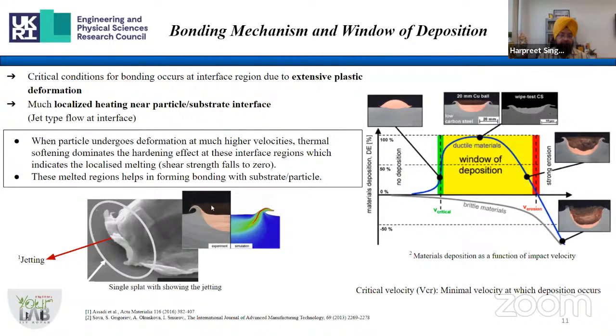Why are we talking about hardening here? Because another aspect which is competing is the hardening, right? Strain hardening, because you are impinging something on the surface, and as both these surfaces, particle as well as the substrate, are plastically deforming, one can expect strain hardening as well. But then temperature also plays a very critical role, and this softening basically dominates, and that's why this particle will tend to deform in this particular fashion, where we get this kind of plastic flow of the material, which we call jetting. This has been shown very nicely through modeling as well. So these melted regions, you can call them, help in forming the substrate and particle interaction.